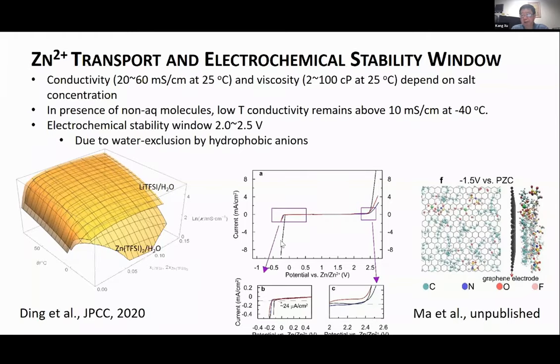Electrochemical window-wise, at the low end, it was actually dominated by the zinc deposition and stripping, which I will talk about later. On the positive side, we don't find any other process except at a very high potential. You do have this oxygen evolution from the water, but overall, it provides us a window of 2.4 volts, which is safe for us to accommodate most of the cathode materials, because the anode side limit was set by the zinc.